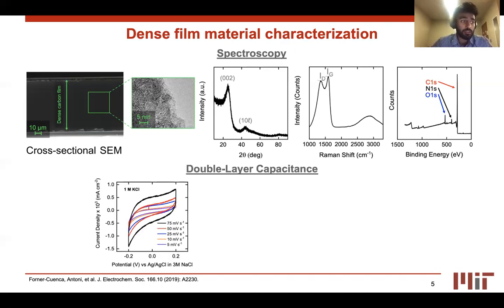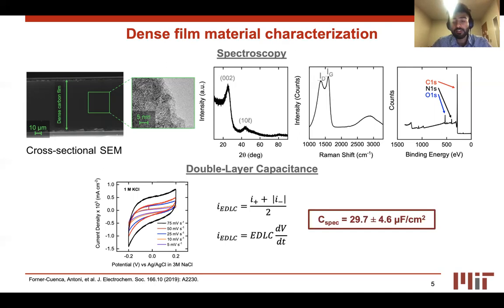A blank 1 molar KCl electrolyte solution was analyzed using cyclic voltammetry to experimentally measure the specific double layer capacitance. The negative and positive non-Faradaic currents were extracted at 0 volts, and the average capacitive current IEDLC was calculated. The electrochemical double layer capacitance was calculated using a linear fit, and the specific double layer capacitance was estimated experimentally to be 29.7 plus or minus 4.6 microfarads per centimeter squared.